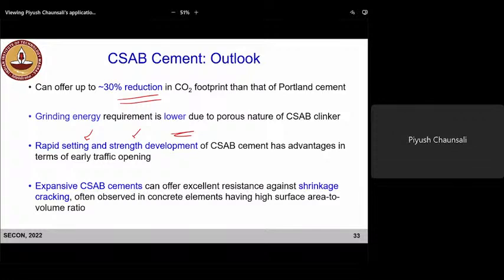And these expansive characteristics, because of the volume increase, can offer excellent resistance against shrinkage cracking. And we know that once the concrete cracks, what happens? We are exposing our steel to atmospheric CO2 or chlorides, and then corrosion starts. And when corrosion starts, that will lead to degradation. So we want to prevent the cracks in the first place. That's the idea. And in this case, the expansive nature of CSAB cement can be used to prevent shrinkage cracking.